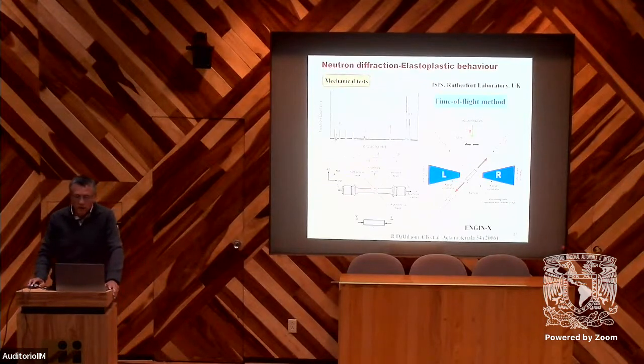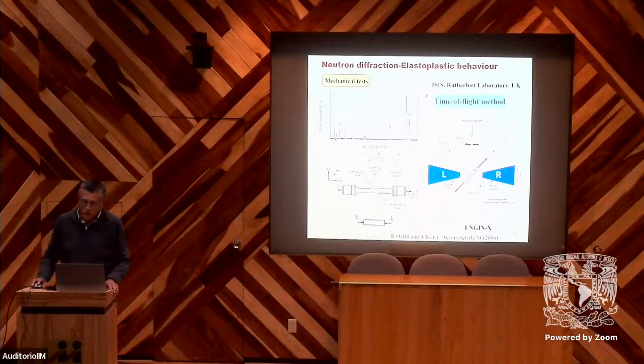The second study is based on the use of the time-of-flight method. For this, we used the spallation source of ISIS in the UK. The advantage of this method is that we can get simultaneously the whole diffraction spectrum, which means we have information on all peaks for each phase.